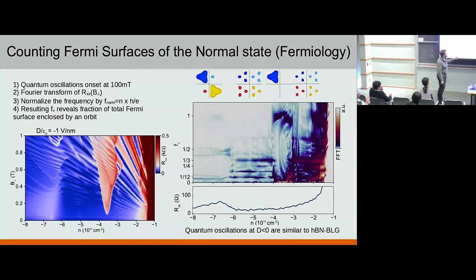I will actually show more data on this, for various configurations, and this will be very important. But you can already see from this plot, which was done at displacement field less than 0, where you expect everything the same as an hBN-encapsulated sample, that in some regimes these lines are easy to interpret. In some of them, much less so. And by staring at these pictures, you end up assigning these diagrams where you can say, oh, this is probably a spin-valley polarized phase here, and so on and so on.